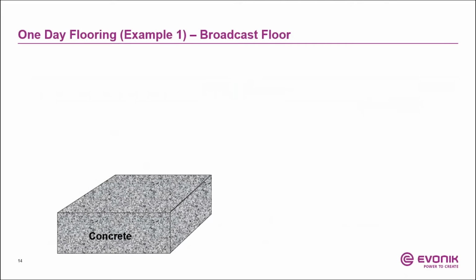All right, so I'm gonna finish up my presentation here by giving a couple examples of a one-day flooring. Here's an example of a broadcast floor. So here you're starting out with a bare concrete. And one thing I didn't mention before is before you apply any coatings on top of the concrete, you really want to prepare the concrete first. So in general, you're doing some kind of profiling, in this case, either shot blasting or grinding, but in general, shot blasting is preferred before applying any coating.